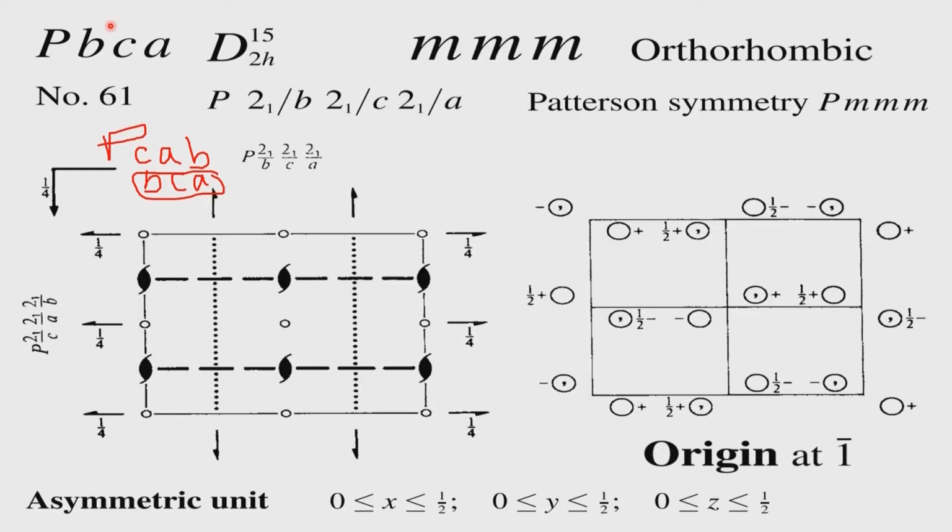If one examines that carefully, you have a solution to the problem. In this particular case, you know that this is a centrosymmetric space group. Center of symmetry is not associated with any axis or any translational periodicity. The periodicity that comes up from a center of symmetry is only one unit along x, y or z. And then of course, it appears also at the half position as a consequence of symmetry. In other words, this center of symmetry position can be also this center of symmetry position or this center of symmetry position.